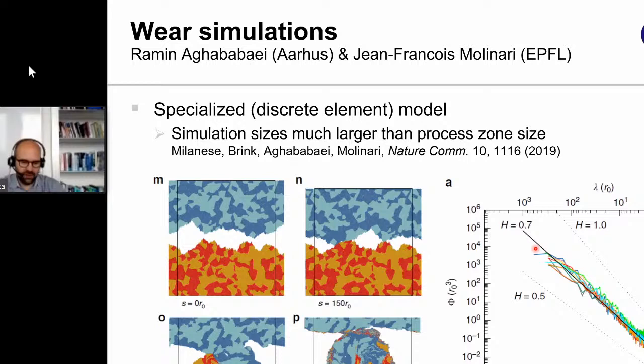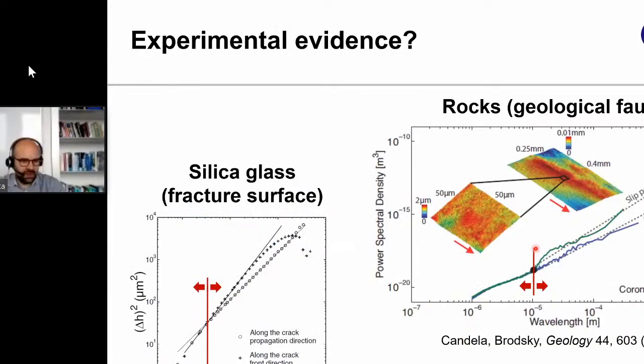At larger scales we have fracture mechanics, which is sort of the gist of this model. And this seems also to be corroborated by experiments. So these are two examples from the literature. The left hand is a crack on silica glass from Laurent Ponson, Daniel Bonamier, and Elisabeth Bouchot that shows that there seems to be a scale below and above which the crack properties change.